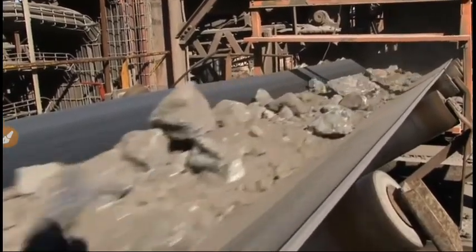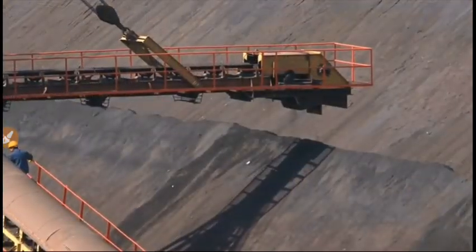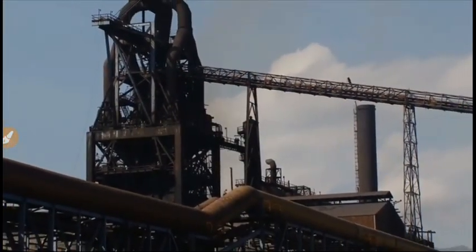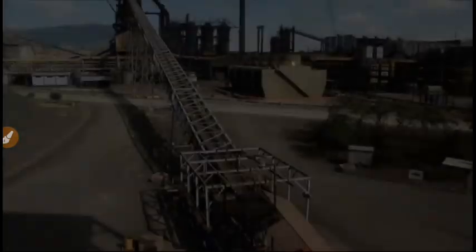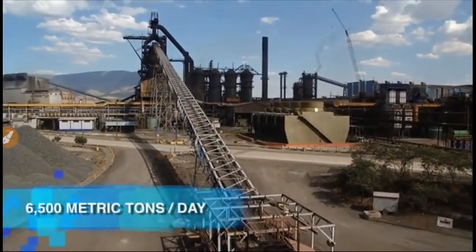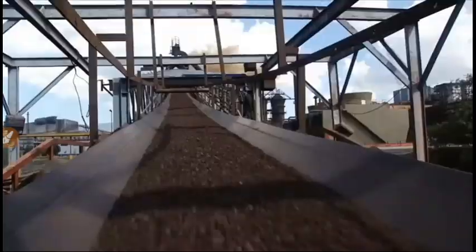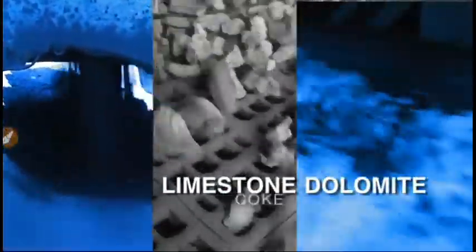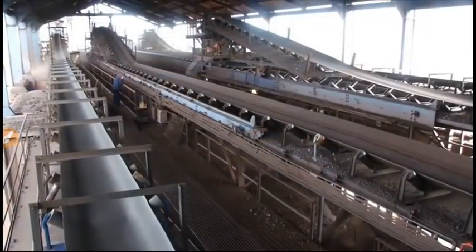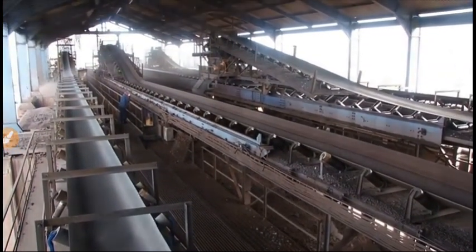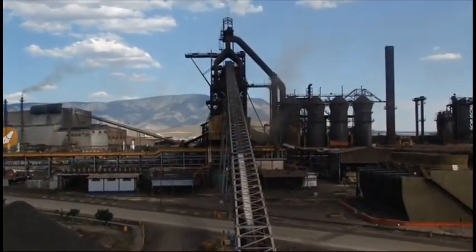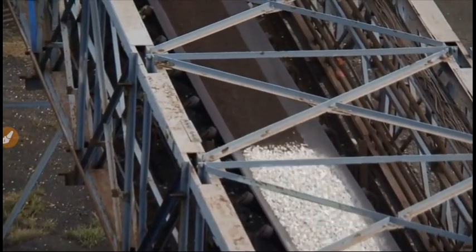Processed iron and coal, the basic raw materials for producing pig iron, are sent to blast furnaces consisting primarily of a large cylindrical structure over 160 feet high whose interior is lined with refractory brick. In the blast furnace, the iron oxides contained in the pellets and sinter, which are stored in a hopper facility, along with limestone, dolomite, and coke, are reduced and converted to pig iron. Mixed in the proper amounts, these raw materials produce layers of various thicknesses when they are deposited in the blast furnaces through the charging system located on the top.